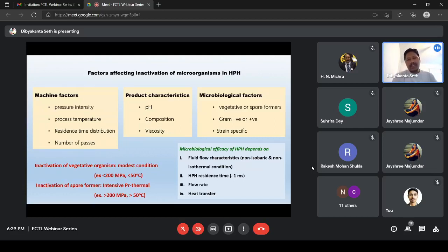But there is still some lacuna in that research: what is the thermal or chemical marker for all these processes, like hydroxymethyl furfural, HMF, production. These chemical markers are still lacking in the high pressure homogenization process. Our traditional way of saying pasteurization is 72 degrees Celsius for 15 seconds, but we cannot define pasteurization in the case of high pressure homogenization. Okay, so there are still a lot of things to do.